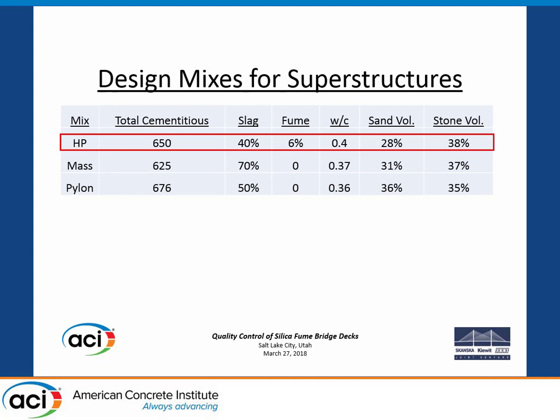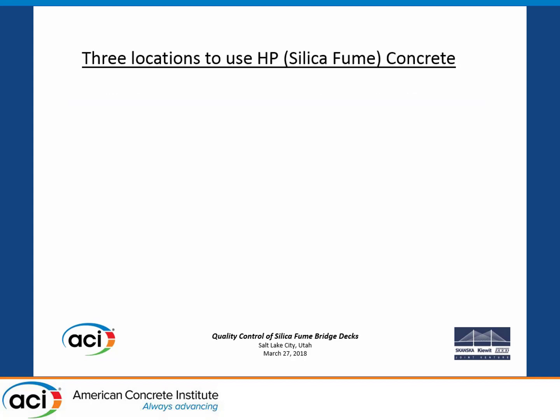That's the big one right there, the HP. If you notice, it's got 650 pounds of cement in it. And 40% of that is slag, and 6% of that is silica fume. Got a kind of a low water cement ratio of 0.40. The other mixes we used was the mass mix, which is 70% slag, and the pylon mix, which we use for the towers on the main span. That's 50% slag. We did pretty well with all of them. The mass mix worked out very well. Stayed nice and cool and gave some real high strength.